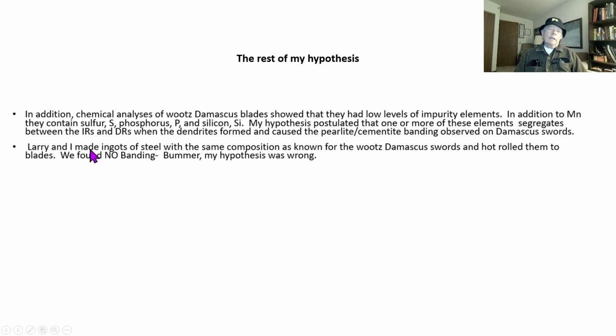So Larry and I made up ingots of steel with the same composition as known for Damascus sword blades. We hot rolled them to blades, since we didn't have a forging mill, but we found no banding. Bummer. My hypothesis was wrong. And that wasn't the first time that happened. That generally happened.